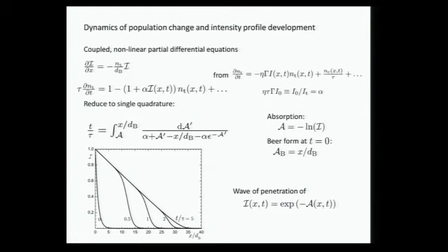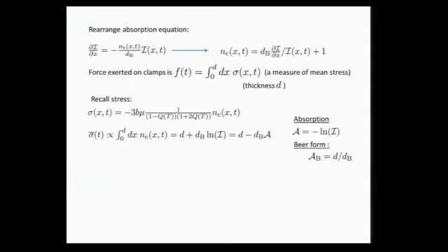So now I'm back to this diagram, and I go from Beer to the deep linear penetration by a bleaching wave which goes through the solid, which is this wave of conversion of trans to cis, where I've depleted the population. So there's an interesting dynamics associated with that penetration, and that is what I'm alleging is the stress.